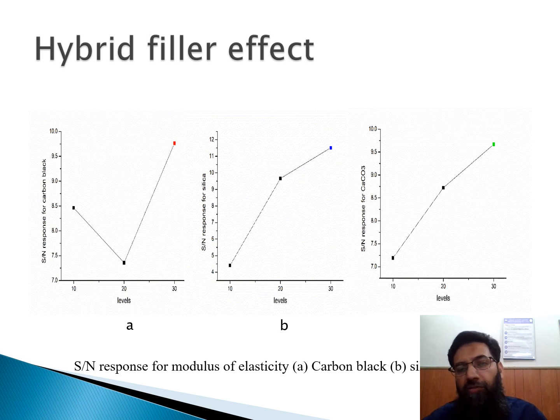If we compare these three fillers for automotive application, silica would be the better option as compared to the carbon black and the calcium carbonate. But still, carbon black and calcium carbonate, due to their cost-effective nature, are more in use in the Pakistani local automotive parts manufacturing industry, because at the moment surface treated silica is more expensive as compared to carbon black and calcium carbonate.